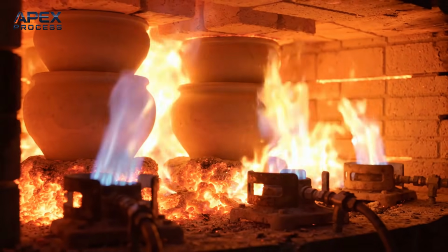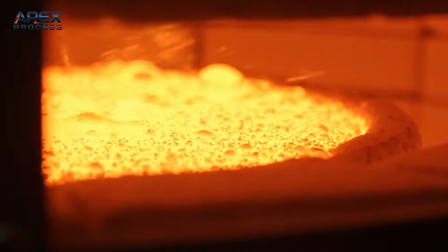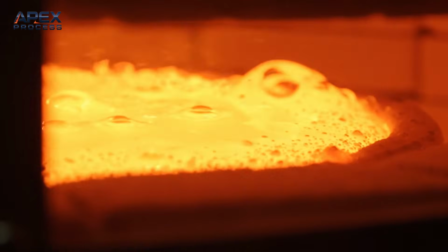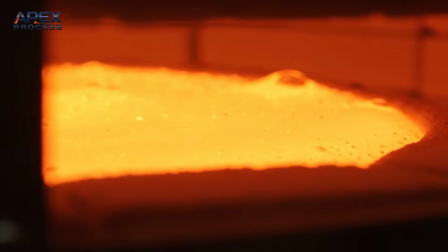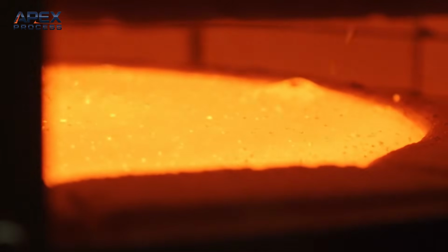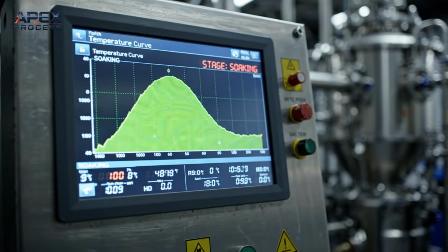This is the point of vitrification. At 1,280 degrees, the clay particles fuse together and the glaze melts into a solid glass layer. We maintain the peak temperature for 2 hours to ensure the ceramic is fully hardened.